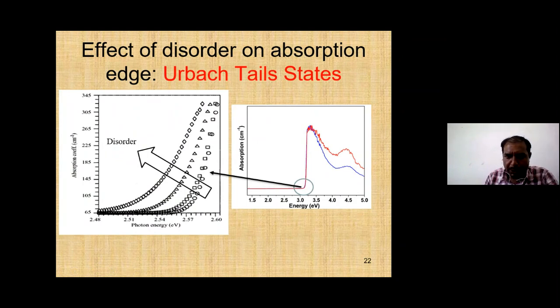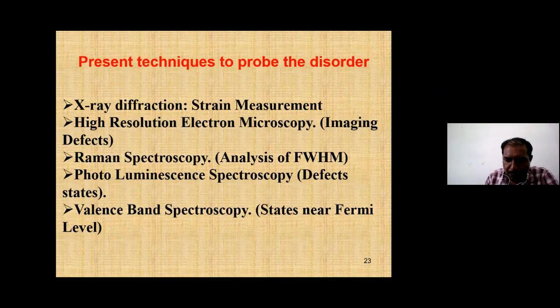So what we have learned so far is that using very simple optical absorption spectroscopy, you can find out the band gap. And further, if you analyze the tail part of the optical absorption spectra, you can also find something called electronic disorder. This is also called Urbach energy in the literature. So you can find out the amount of electronic disorder present in your samples. This disorder is essentially due to some type of defects or disorder present in your samples.